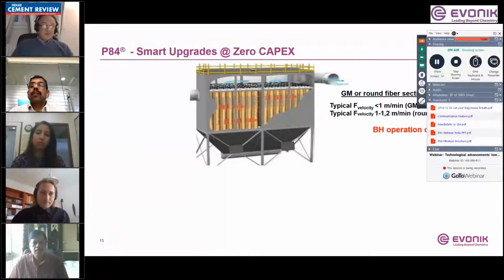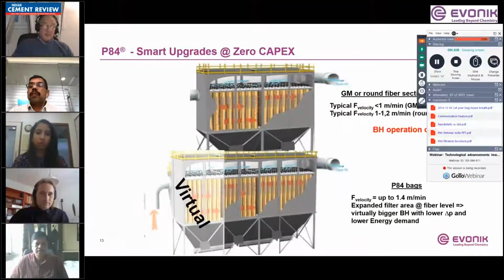So promising your process filter a second life, which is the title of this presentation, really means that. By adopting P84 media, you would virtually increase the filter surface of your bag-house without needing to add any compartment. That means zero capex. In fact, P84 fibers provide an extended specific surface at microscopic level, as shown in the previous images, which allows your bag-house to operate at higher air-to-cloth ratio up to 1.4 meters per minute without requiring additional compartments. This is quite something, I believe.